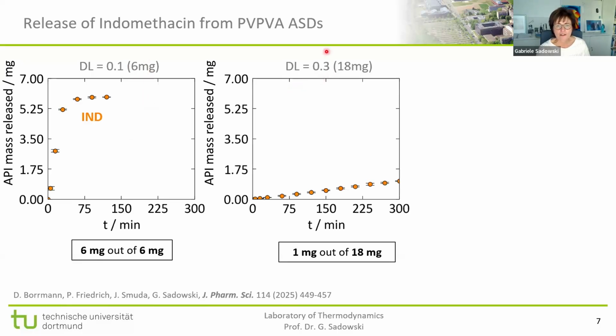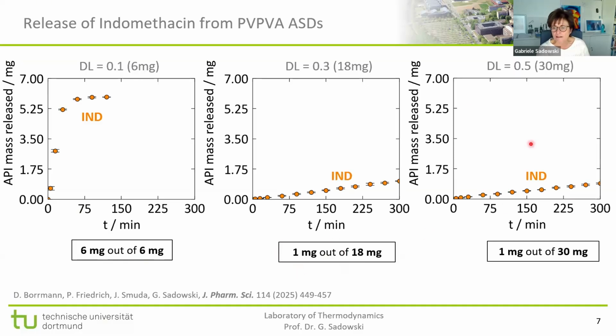So if we go to a drug load of 0.3, we have 3 times the amount of the drug load 0.1. Now we have 18 milligrams in the sample. But due to the breaking down of release, even after 5 hours, we have released only 1 milligram out of 18. So here we have 6 out of 6. We increased the overall amount to 18, but now we have not 18 out of 18, but we have even less than the 6 we had here. So that means tripling the drug load means that we have now almost no release anymore. And this, of course, for 0.5, gets even worse.